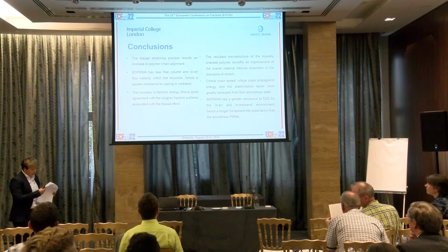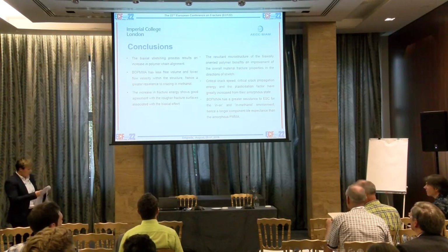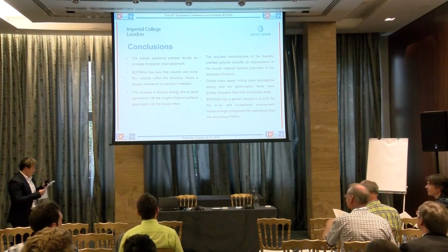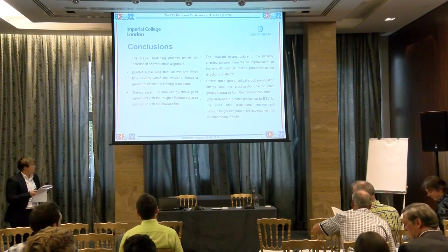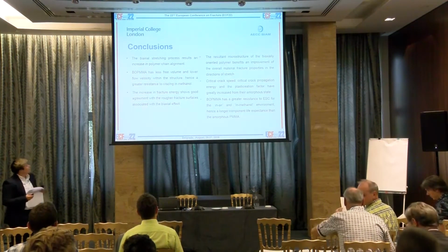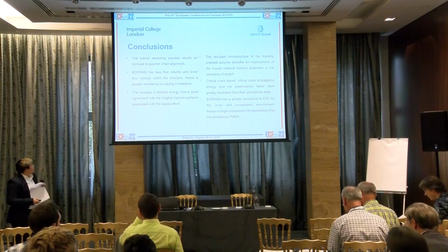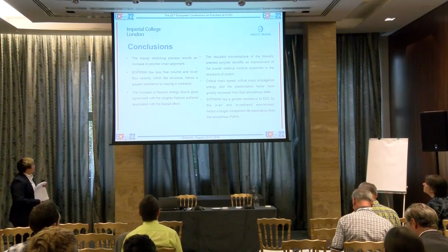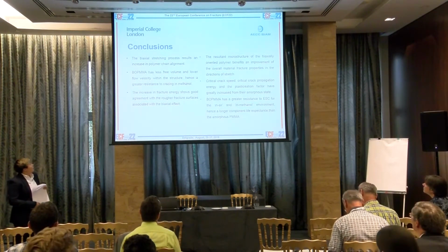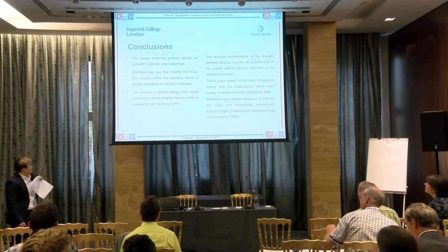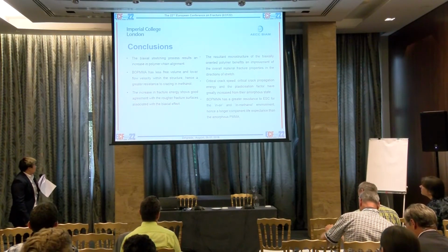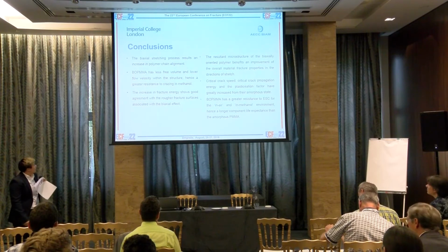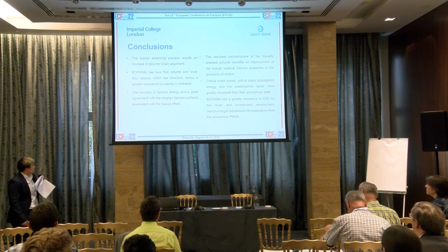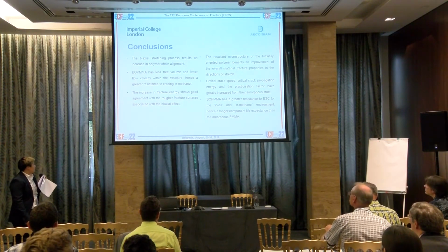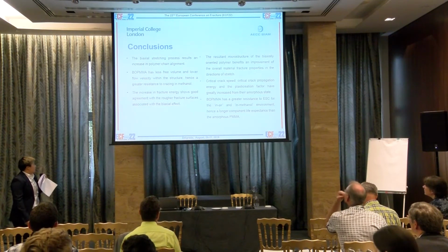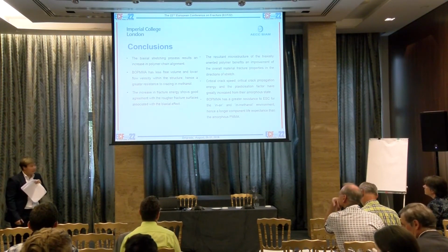And here we have the conclusions. The biaxial stretching process results in an increase in polymer chain alignment. The BOPMMA has less free volume and lower flow velocity within the structure, hence a greater resistance to crazing in methanol. The increase in fracture energy shows good agreement with the rougher fracture surfaces associated with the biaxial effect.